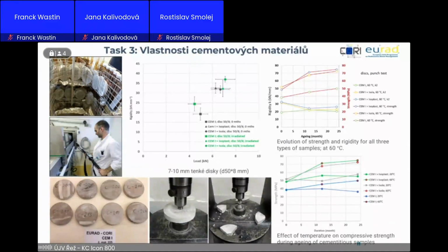This test is about the rigidity. I damage the sample by some load, and I'm measuring the displacement. On the graph in the middle, I'm showing the load of the destruction, but also the displacement, or the rigidity. The black points represent the samples without radiation, and the green ones represent samples irradiated by 7 megagrays. You can see that, for example, for STEM without plasticizer, the load is a little bit the same, but the rigidity, like modulus of elasticity, is higher. So in this case, radiation didn't damage the material.